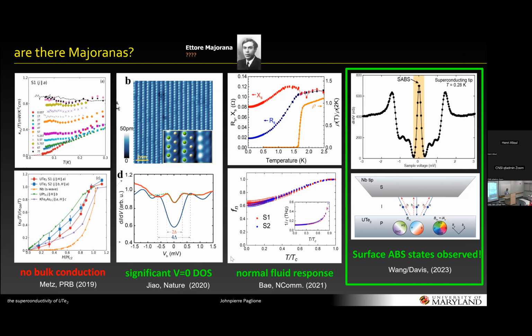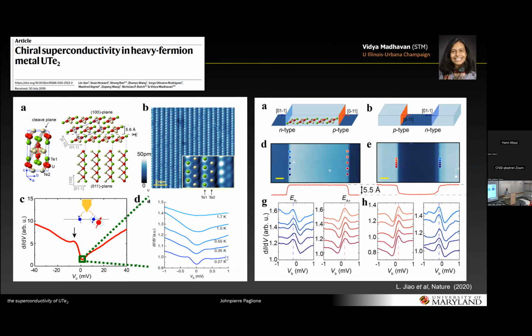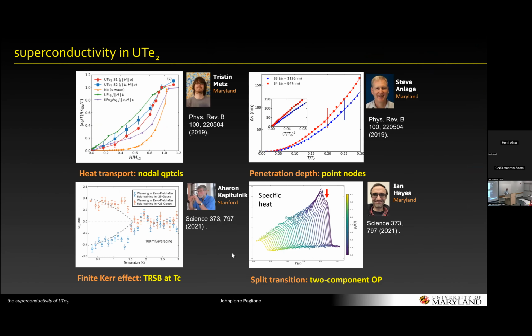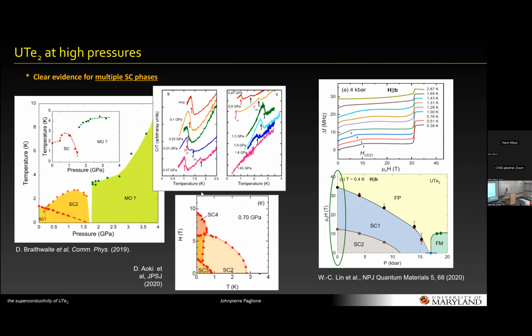Now, I'll just end with saying that with all this about the ambient pressure superconducting state, you have to remember that, I skipped completely over the pressure dependence, but there's no ambiguity that when you apply pressure to this material, the TC splits into two TCs. And there's one TC that goes up to about 3 Kelvin and one that drops off and disappears by about 1 GPa. And there's specific heat data and there's several experiments. In fact, if you go in some regime of pressure and magnetic field, Aoki-san has shown that there's up to 4 superconducting phases. So even though there's a strong debate about this ambient pressure superconducting phase, whether it's a single component, 2 component, 2 TCs, 1 TC, all this stuff, apply some pressure and you split TCs very obviously, and there's at least 2 superconducting phases. So at ambient pressure, there's got to be some near degenerate state that's very subtle. So I don't think it's that simple to just say B2U.